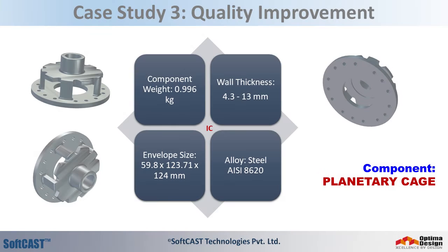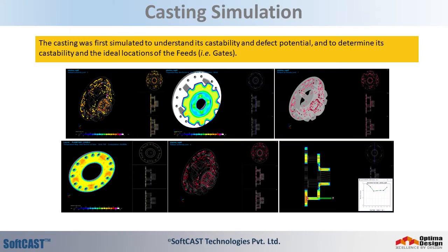Our third case study is a quality improvement project for a 1 kg planetary cage alloy steel casting. This was at a medium-sized IC unit in North India. Results of the casting simulation, that is the hotspots, temperature maps and thermal traces, clearly showed the defect potential, the solidification zones, and the required locations of the gates.